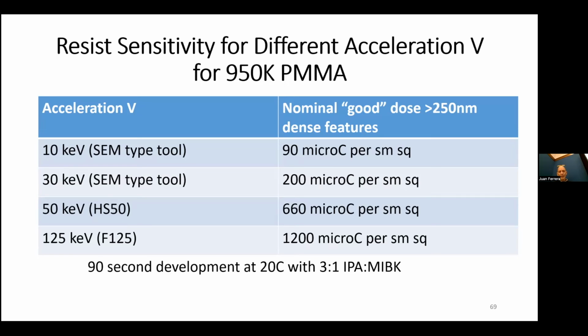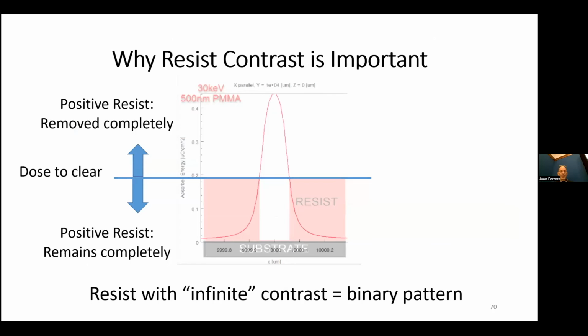I put this in here because if people email me after the talk, I will send this talk back out again. I think it's a generally useful reference of approximately the different sensitivities for a classic 950 K PMMA developed at room temperature for about 90 seconds with 3:1 IPA:MIBK for sort of semi-dense features that are bigger than 1/4 of a micron. You know, these are approximately good values to start with.